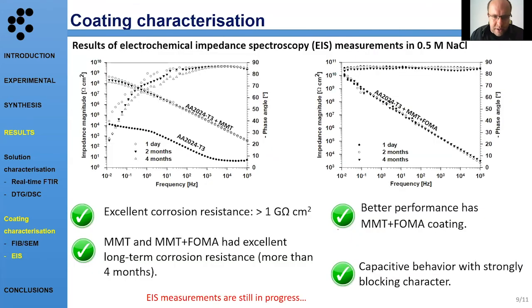And here, finally, the electrochemical impedance results. So the aluminum alloy without coating has, of course, very low impedance values. But after coating with this hybrid sol-gel coating, we can see the impedance value increases by a few orders of magnitude to much higher values. That means that this kind of coating presents very good corrosion resistance.